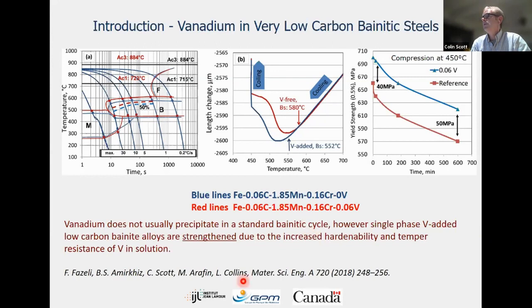So here's some data that has been published in 2018 from our group at Canmet. This is Fateh Fazeli, who's the lead author. And you can see the effect of the vanadium on the TTT diagram. And also here is very clear what's happening: when you look at the dilatometry data, the BS start temperature has been dropped from 580 to 552 degrees C. It means that you're getting more lower bainite, essentially, and that's where your strengthening comes from.